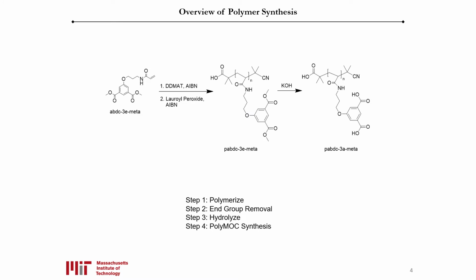After synthesizing our monomer, we then polymerized the monomer to make a polymer. We removed the end group on our polymer. We hydrolyzed the polymer, and then we created hybrid polymer metal organic cages.